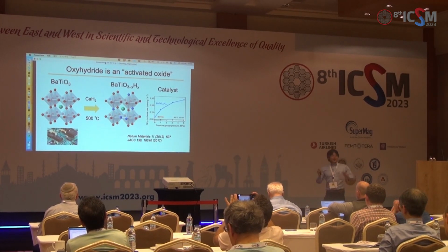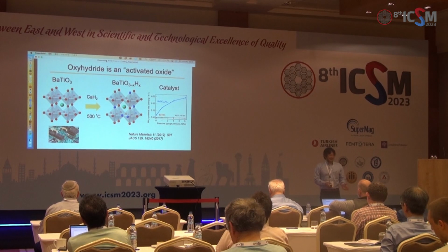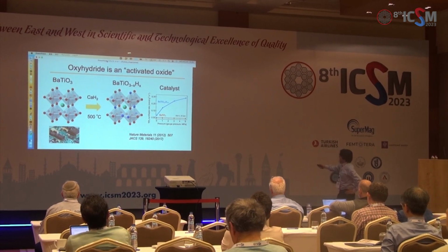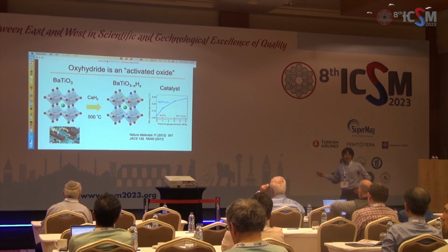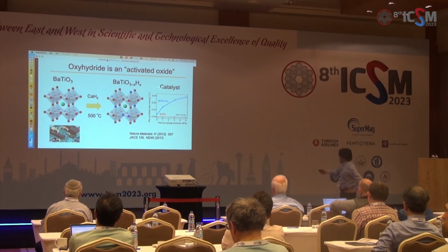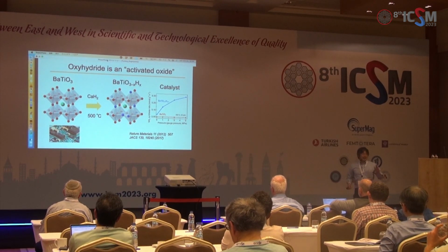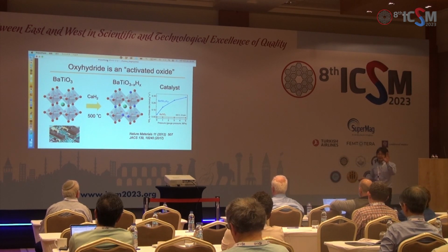So hydride anion is less stable than oxide anion, and which may give a very nice playground for reactions of chemistry or catalysis. We observe this very nice catalytic activity, which is the ammonia synthesis catalyst in these materials. So this is one of the highlights of the mixed-anion compounds. Okay.